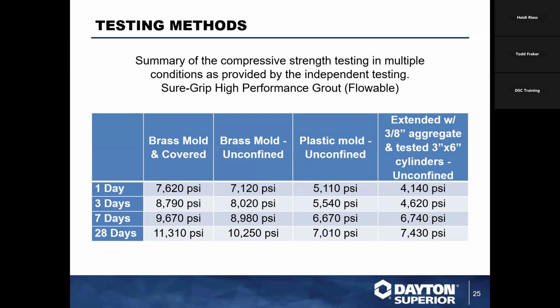Our published strengths are based on a C109 test, which is a particular geometry for the sample. It is maintained at a particular temperature for a particular period of time. I can't tell you how many times I've gone to a job site and they're testing the grout like concrete. They're putting it in a large cylinder, and those cylinders are like 5 by 8.